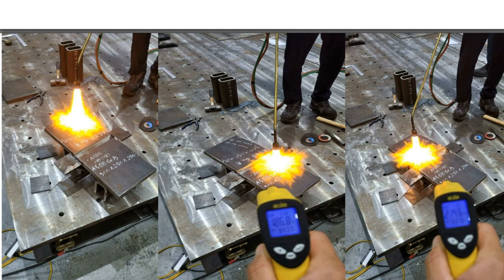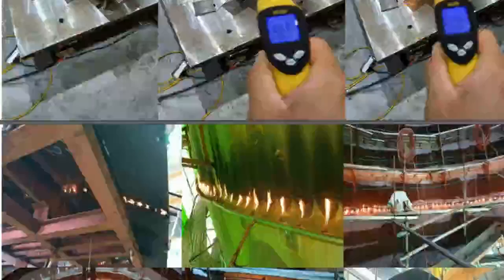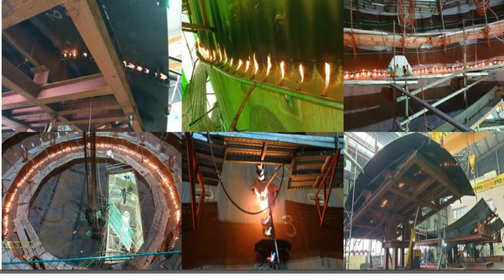You can see the temperature here, in degrees Celsius, 186.8. So the temperature for the preheat is pretty high, since this is a low alloy material. As I said, preheat is really important for ferritic materials, including carbon steels. And these pictures are preheating for sphere tank fabrication.